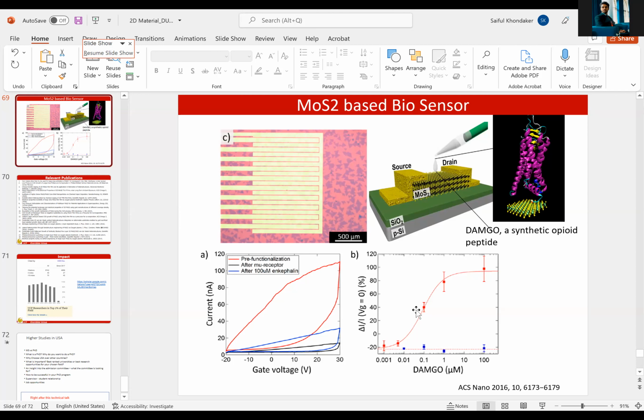Over most of the time we see this. But when you do sensing, there are two important things. One is sensitivity, the other is selectivity. Yes sir. So the more important thing, okay, I know the current is going to change, as I showed you. I mean, anything that you put on 2D material, the current will change because it will do a surface charge transfer. But the point is, how do you know that's the molecule? So you have to create an antigen antibody reaction, right?